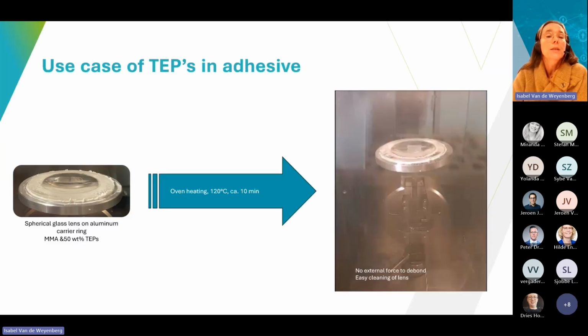And in the next slide, you see here also a nice example. We have a spherical glass lens, which is mounted on an aluminum carrier ring. And when we put the complete part in an oven at 120 degrees for about 10 minutes, this is what's happening. We see the foaming of the adhesive. And I will stop the image now. You see the adhesive is really foamed up.